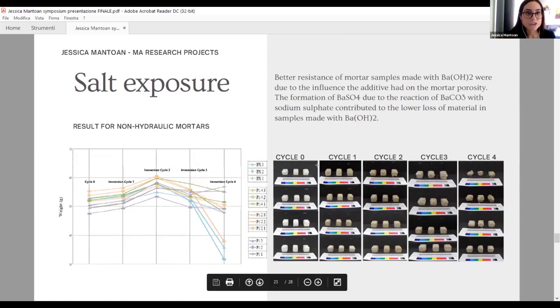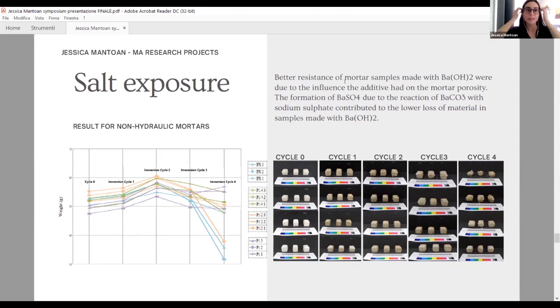The same result is visible also for non-hydraulic mortar, where it's even more evident because we have more samples, and we can see that for PX, so the sample that doesn't contain any barium hydroxide, after 4 cycles my samples were completely destroyed. While moving through increasing addition of additive, we can see that the material is in a better condition. This is again due to the formation of barium sulfate, so barite, which is insoluble and allows the salt not to interact with the lime, but to interact with the barium.